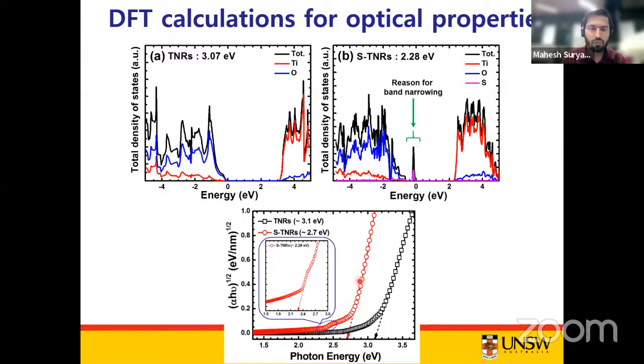We also carried out UV-visible spectroscopy measurements, and we realized that the sulfur-doped TiO2 nanorod arrays show a band gap value of about 2.7 electron volt. However, if you zoom the spectra and focus on the region from about 2.2 electron volt to 2.5 electron volt, you can see an additional tail. And if you calculate the band gap from this additional tail, the band gap value comes to about 2.28 electron volt, which further confirms our observations from the DFT calculations.